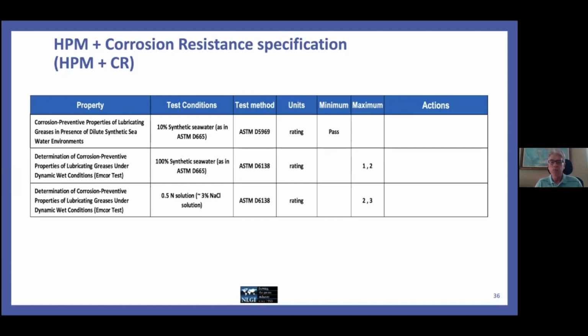And again, with a fair bit of discussion back and forth on the appropriate maximum limits, we agreed on a 1,2. And what that means for those of you that aren't familiar is you're running 2 bearings and you're allowed to have one of them be a 1 and the other one be a 2. You can't have 2 bearings that both test at a 2 or you've failed. So you have to be at least 2 or better on one bearing, and you have to be at least 1 or better on the other bearing.